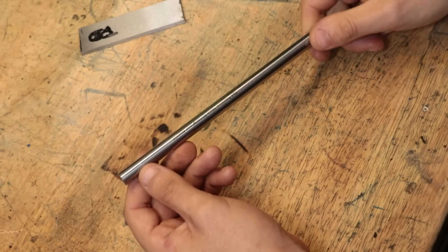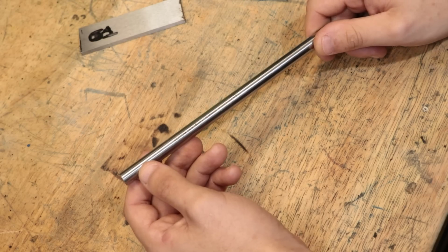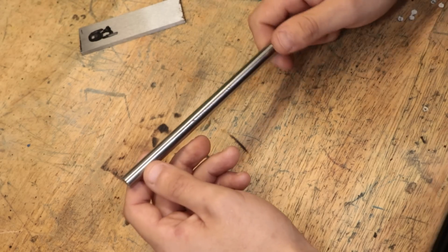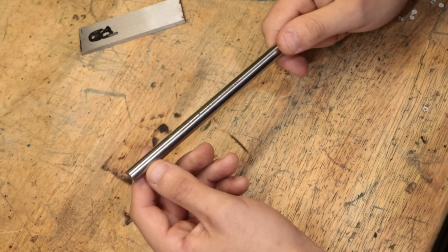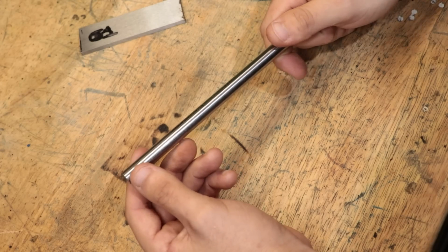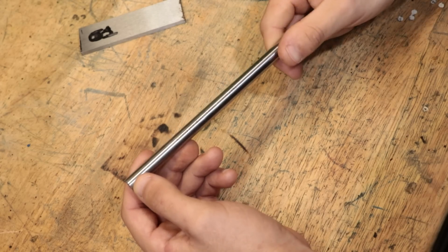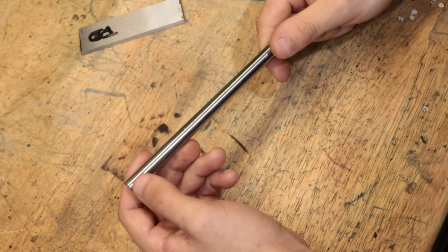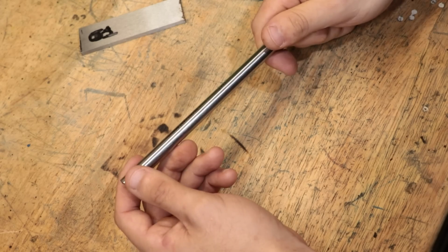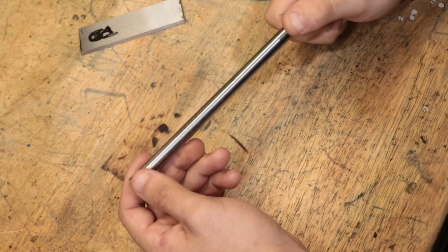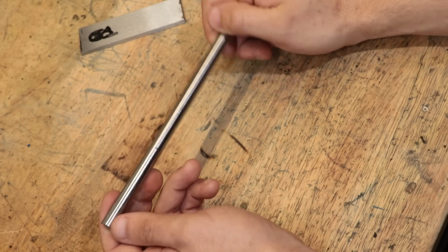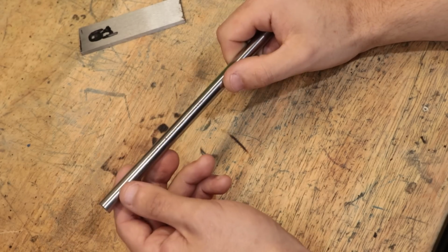However, because I am quenching it in water, the risk of the part distorting if I don't get it cooled evenly is relatively high. And if that happens, I either have to re-anneal it and reshape it, or I have to grind it into shape. The part can also crack due to the thermal shock, or if the part is warping too much, and if that happens, that is pretty much a scrapped part.